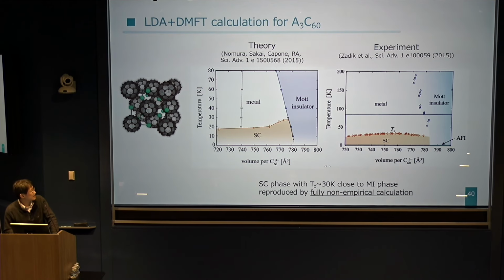This is the phase diagram in the plane of temperature and volume of the unit cell. Volume of unit cell means, roughly speaking, pressure. So it is a PT phase diagram, and we have a Mott insulating phase. LDA cannot describe this phase diagram. But if we perform LDA plus DMFT, then we can reproduce the superconducting phase and the Mott insulating phase.